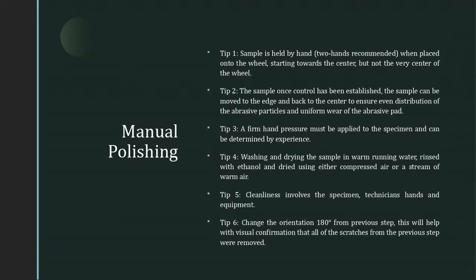Tip number 4: washing and drying the sample using running water. Warm water is preferred—just like when you wash dishes, it dries faster and cleaner, more spotless. Then you rinse it with ethanol, and you can dry it using either compressed air or a stream of warm air if there happens to be a hair dryer in the laboratory.